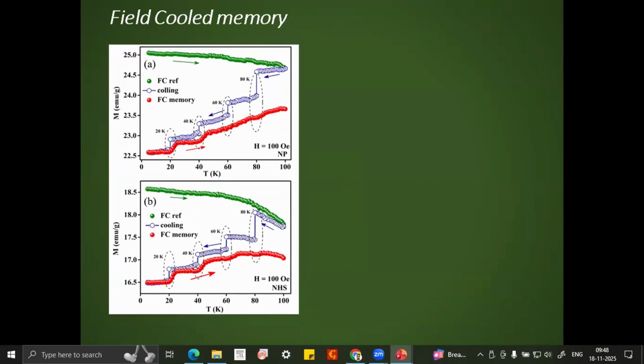With this, we proceed to the field cool memory effect. Now, this is kind of a conclusive evidence. In the field cool memory, first of all, we record the field cool magnetization curve. This is called the FC reference curve, marked in green. Then after coming to 100 Kelvin, we cool down the system to 5 Kelvin with the application of 100 Oe magnetic field with intermittent halts at 80 Kelvin, 60, 40, and 20 Kelvin. During each halt, we switched off the magnetic field and allowed the system to relax for around 1 hour. After coming to 5 Kelvin, in the presence of the same 100 Oe magnetic field, we now measure the magnetic moment in the heating cycle.